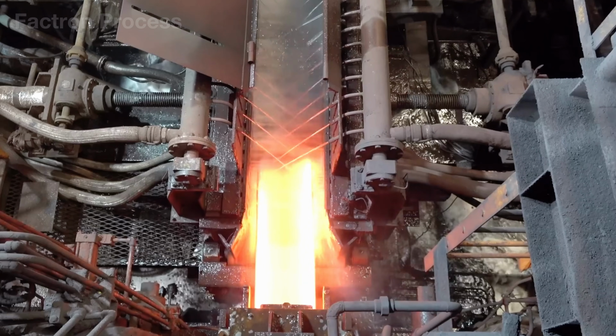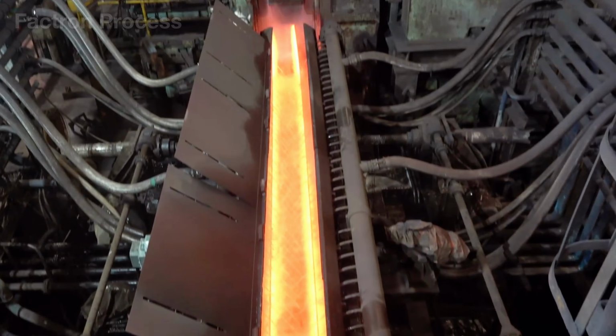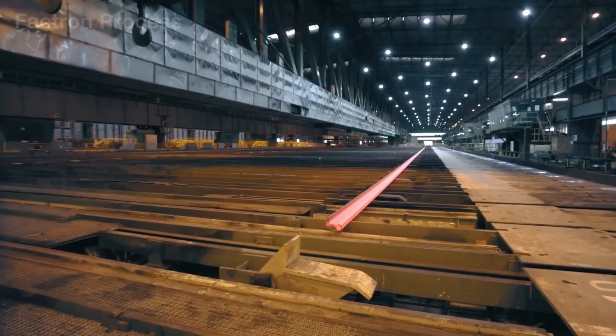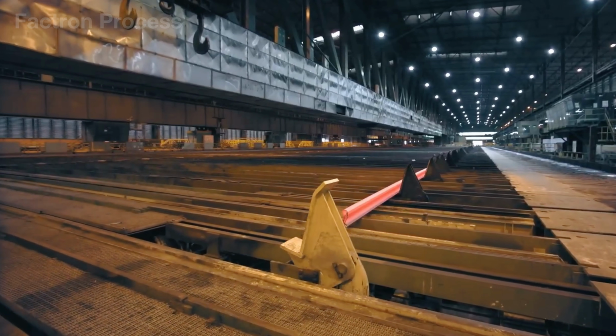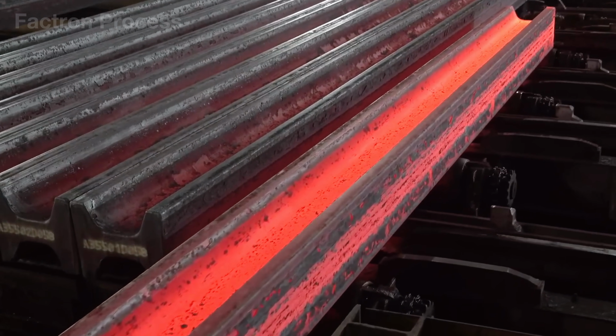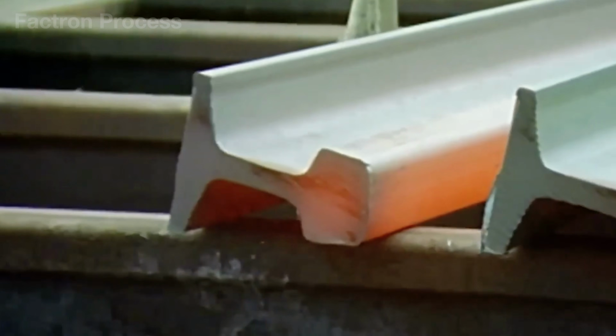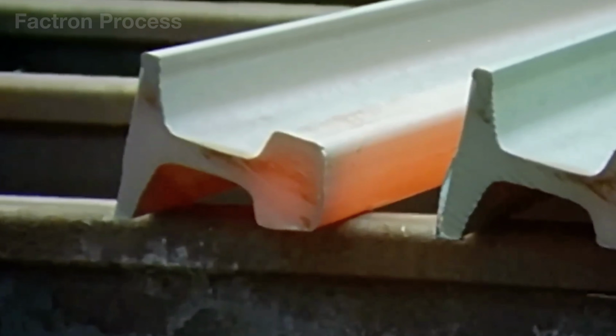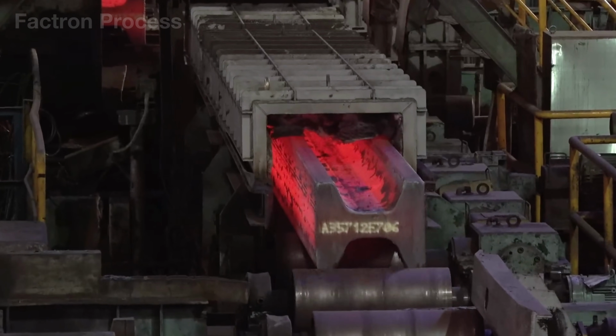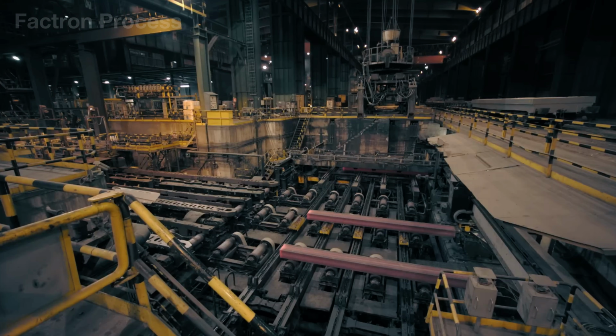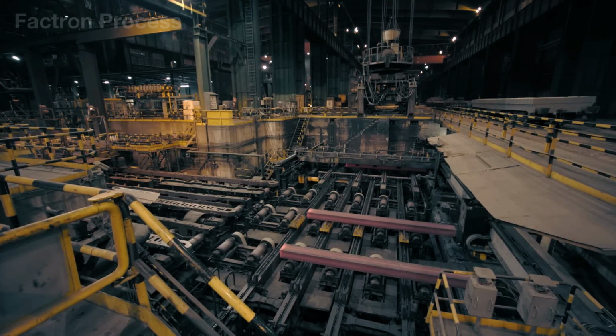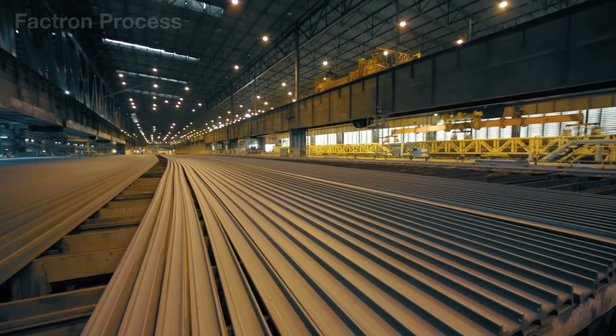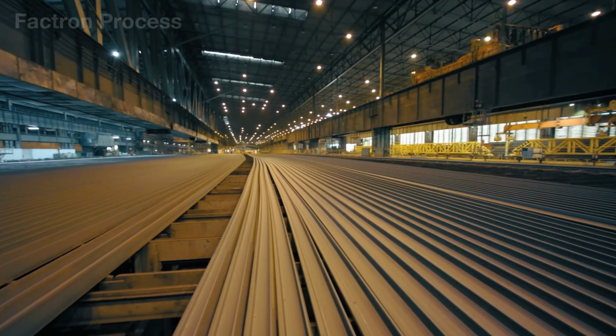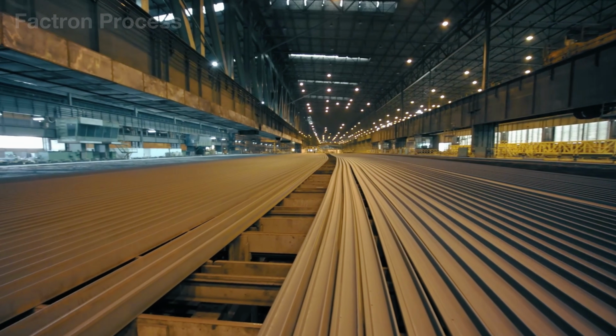This transforms the hot steel structure into ultrafine pearlite, raising the railhead hardness to approximately 350 to 390 HB and greatly improving wear resistance. The cooling rate must not be too rapid. If brittle martensite forms, the railhead may crack under the repeated loads imposed by passing train wheels. After natural cooling, the rails may still develop slight warping due to uneven thermal shrinkage stresses.